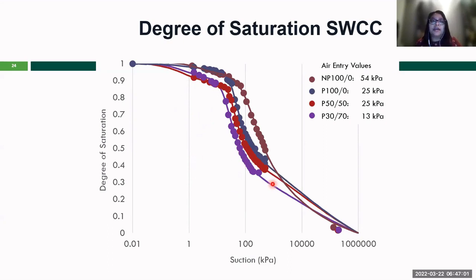Polymer amended may also contain higher residual water, and the non-polymer air entry value was bigger. If you see the value, which is 54 kPa, that's a shrinkage effect. And then polymer material has no change on the air entry value. So there is no shrinkage effect there. So that's the major difference between these two types of material. So non-polymer has a shrinkage effect and shows the high air entry value, and polymer treated material didn't have the shrinkage effect.